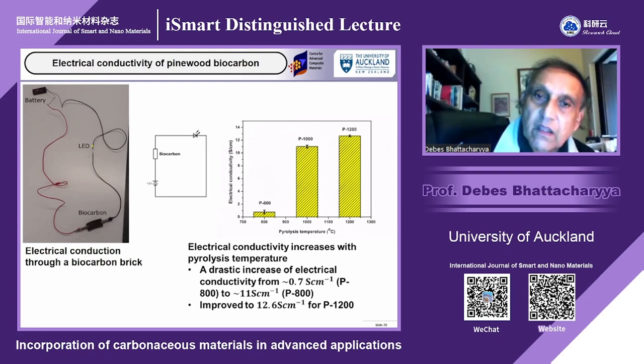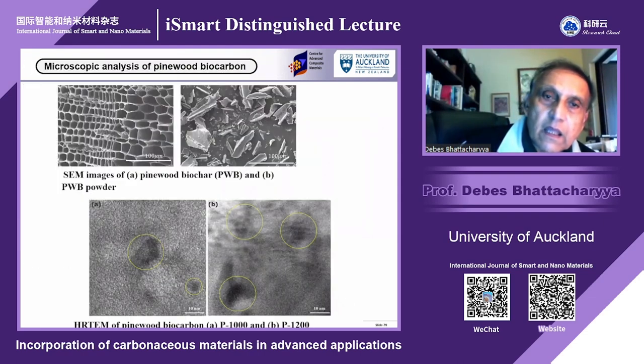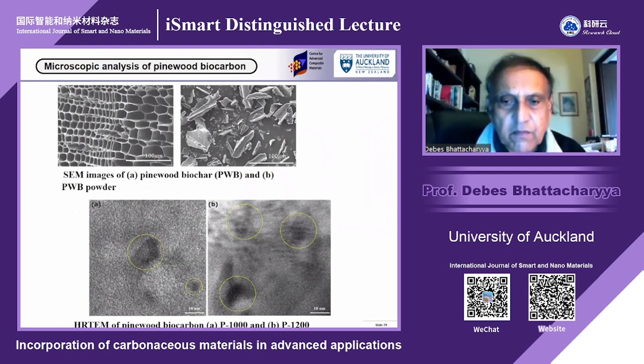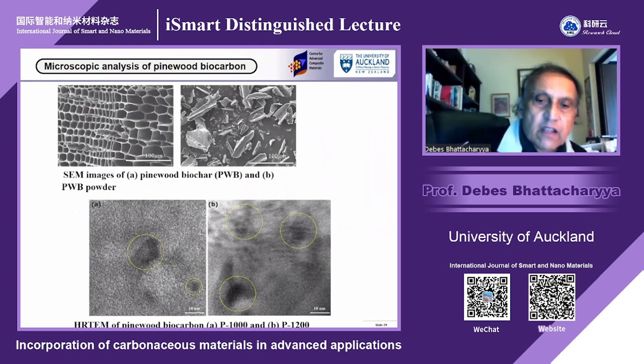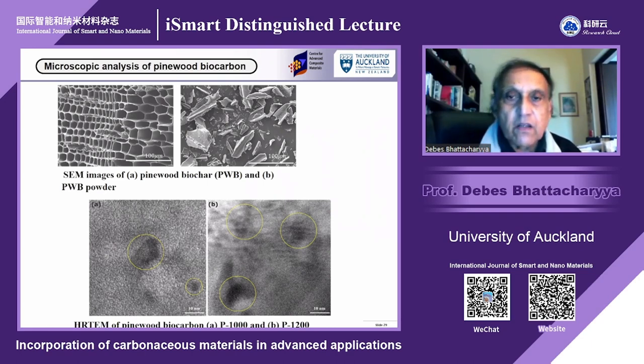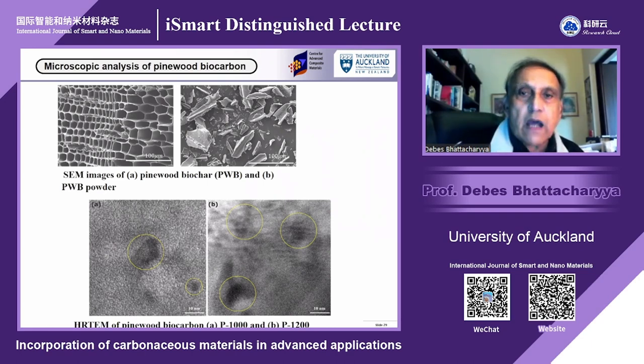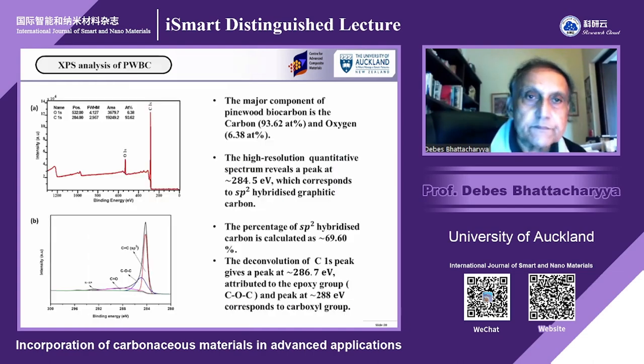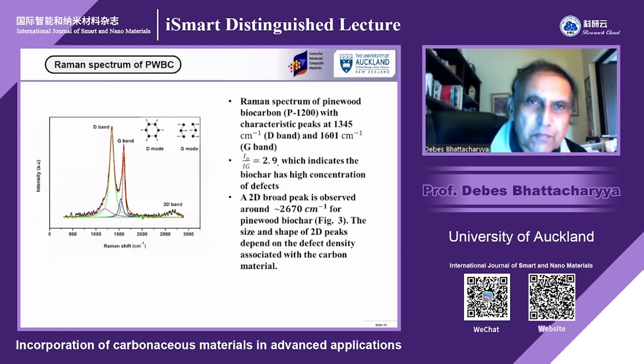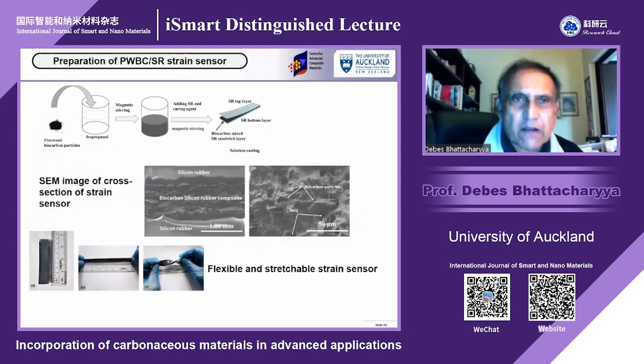Justin is writing up his thesis, and then we'll have these results. These are some of the things showing how it changes from 1000 degrees centigrade to 1200 degrees centigrade, how the honeycomb structure is completely broken into this kind of powder form after pyrolysis, with graphitic clusters. Let us not spend time on the Raman spectrum. We have done all those things.